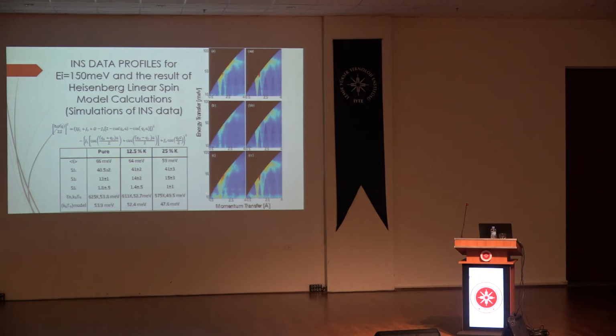Especially if you look at that, there is an intensity here, and that intensity is caught in the analysis. This is not a phonon background intensity, that is unreacted manganese oxide. Manganese 1, oxygen 1. Manganese 1, oxygen 1 is also an antiferromagnetic material. We will see it later.